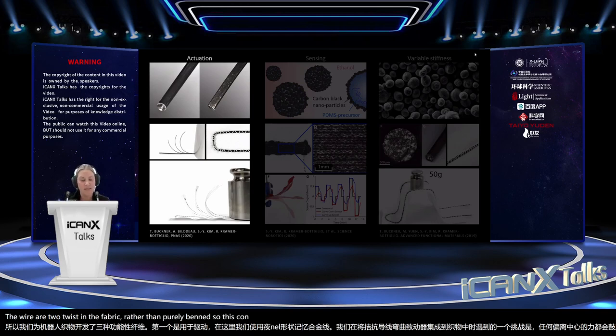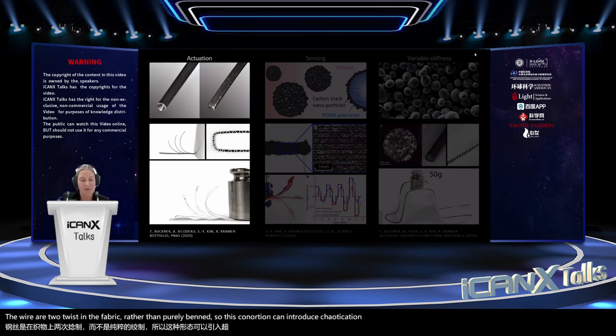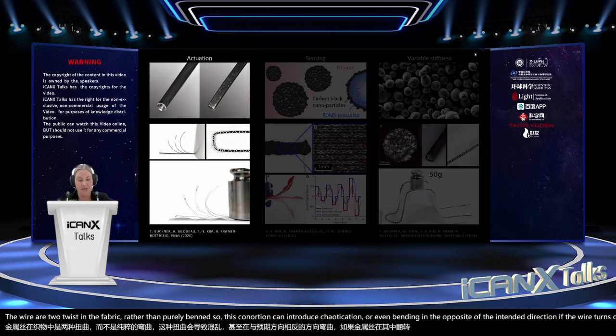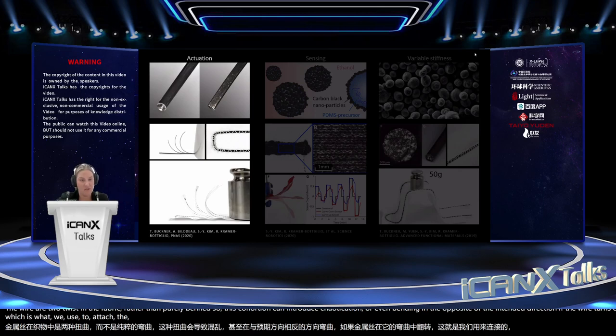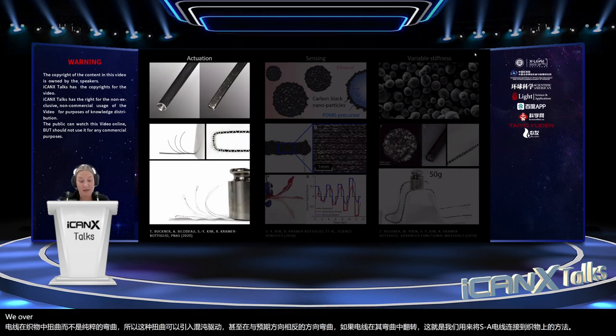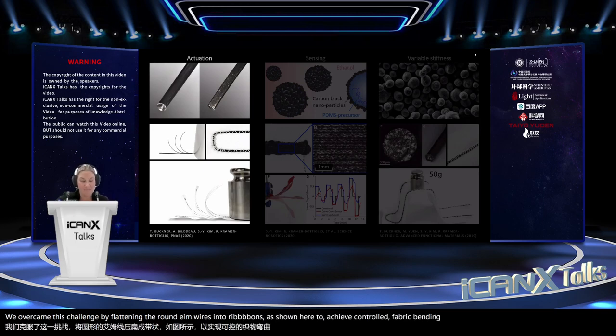So this contortion can introduce chaotic actuation or even bending in the opposite of the intended direction if the wire turns over within its couching, which is what we use to attach the SMA wire to the fabric. We overcame this challenge by flattening the round SMA wires into ribbons, as shown here, to achieve controlled fabric bending.